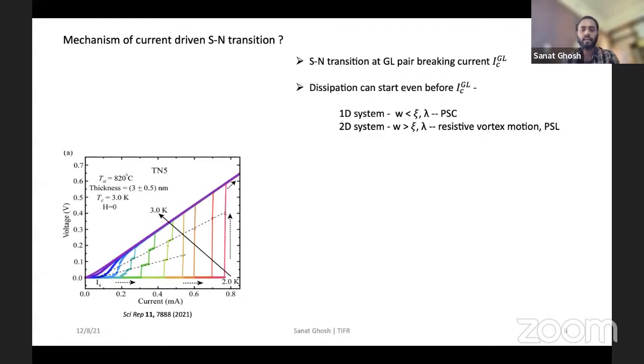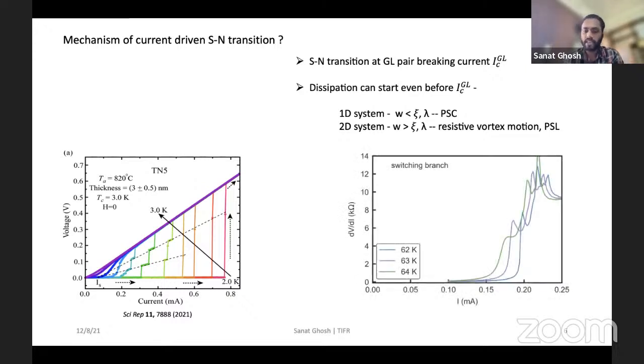Now, a typical identity of this phase slip center or phase slip line occurs in the IV characteristics, where you have multiple jumps from the superconducting to normal state. And in our device, we similarly see this kind of behavior, which seems to suggest that the phase slip line can be a mechanism by which the superconductor becomes normal.